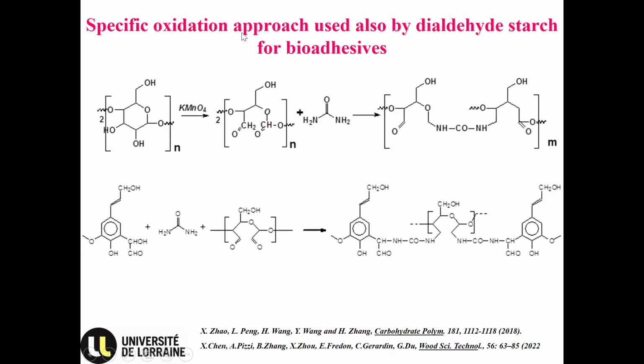You've also got specific oxidation approaches using dialdehyde starch. Dialdehyde starch is produced industrially in China, for instance, but it can also be produced easily in a laboratory, or by anyone. The industrial one is produced by using hydrogen peroxide. And this was a system proposed by the Chinese. They use potassium permanganate to form the dialdehyde groups and cross-link the starch with urea. There is no formaldehyde here. It gave very nice adhesives. Also, you can react urea with pre-glyoxylated lignin and starch. You can have a mixed adhesive in which the urea is the cross-linker that is also resistant to water, when the first one, the top one, is not resistant to water.